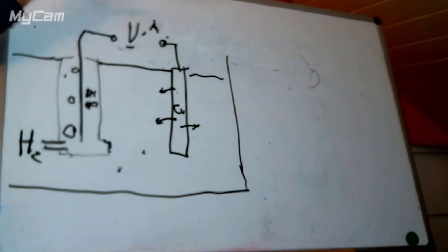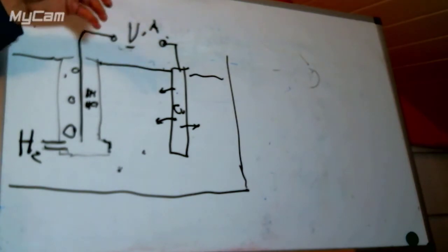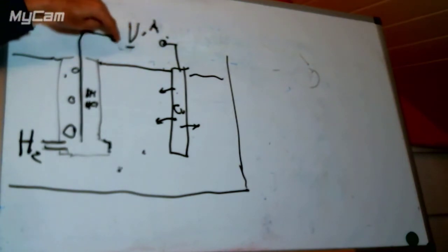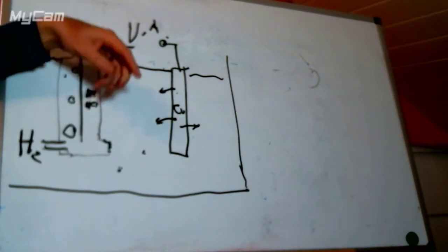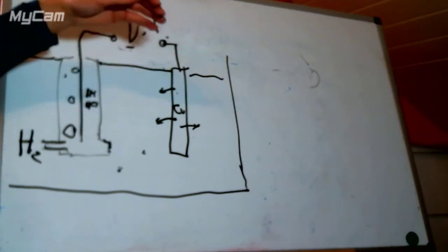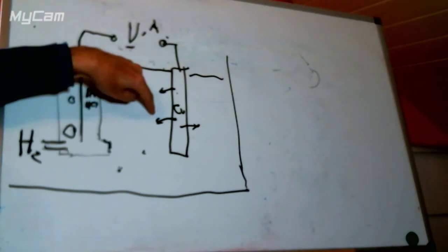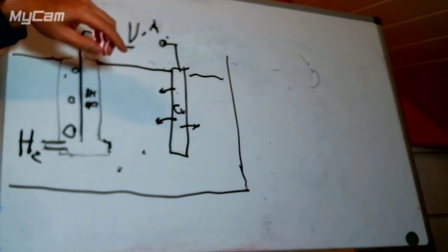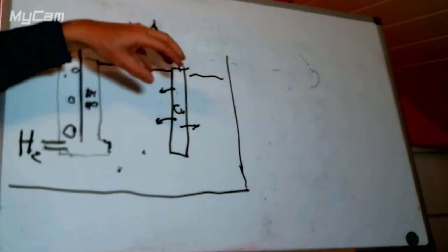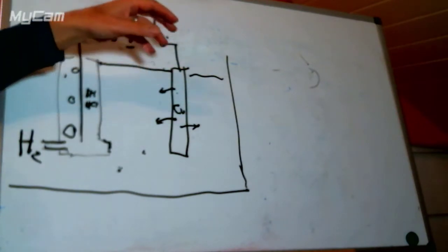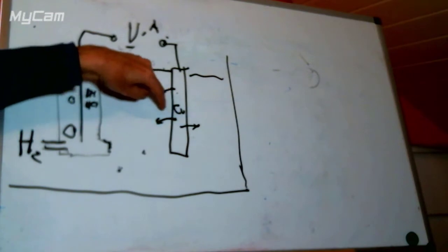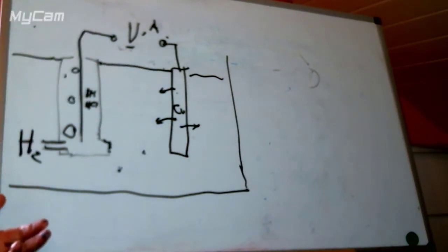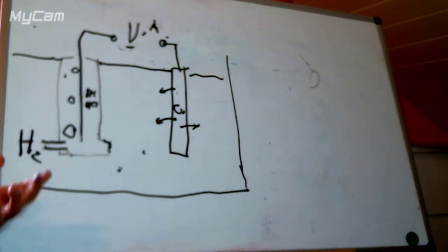So then we're at equilibrium, we do nothing. If we have a voltage that's more negative than the open circuit, where it would go on its own, then we're forcing the copper to deposit. And if we have it more positive than open circuit, we're forcing the copper to dissolve, where thermodynamically it wouldn't normally. We're using voltage to change things.